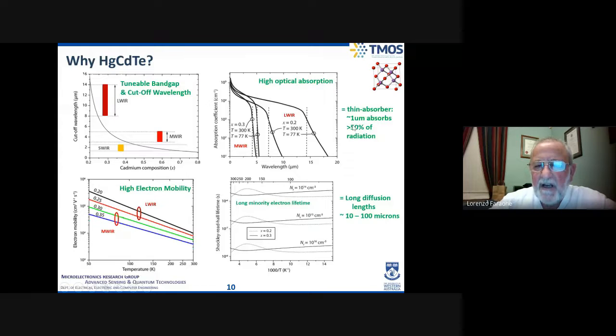So this high absorption coefficient means I absorb all the photons and generate electron hole pairs, and this high mobility combined with a long lifetime gives me a long diffusion length, which means I can collect those electron hole pairs very efficiently, giving me the photocurrent in the external circuit, which of course is my signal.